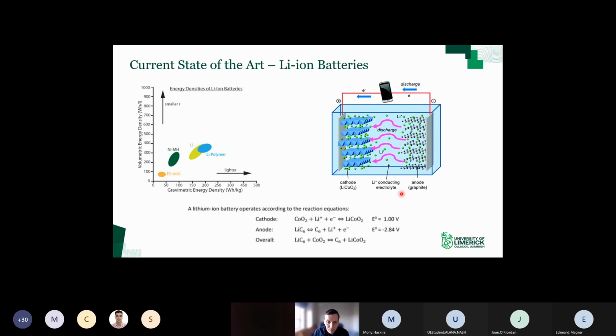The operating principle of a battery is basically you have an anode and a cathode, separated by a polymer separator that's soaked in electrolyte, generally carbonate based. At the cathode, conventional materials are layered oxide materials, something like lithium cobalt oxide, although there's a move away from cobalt now towards nickel and manganese. You can have polyanion type compounds as well at the cathode, something like lithium iron phosphate.